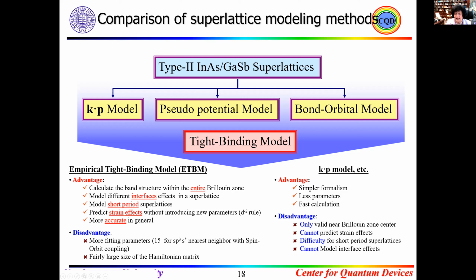And the disadvantage is that it is only valid near the Brillouin zone center and cannot predict the strain effects when we have this material in the larger, as an example, gallium antimonide, and there is difficulty for short period superlattices, and it cannot model interface effects. But if we go to the tight binding model, the empirical tight binding model has many advantages: it calculates the band structure within the entire Brillouin zone, models different interface effects in a superlattice, can model the short period superlattice, can predict strain effects, and at the same time is more accurate in general.